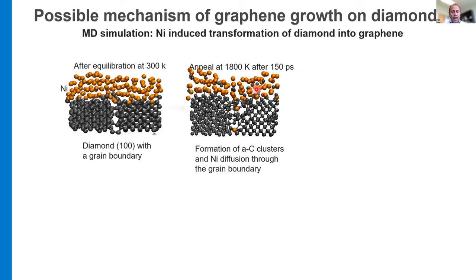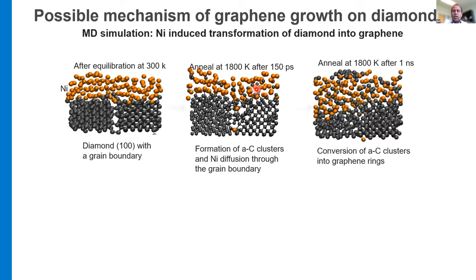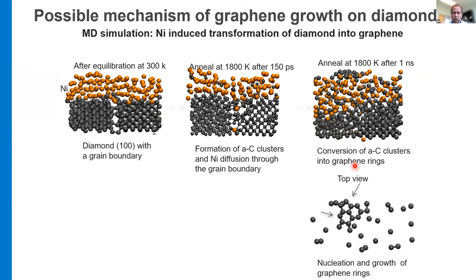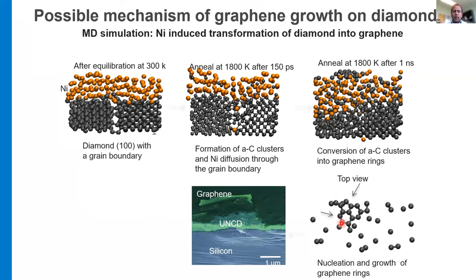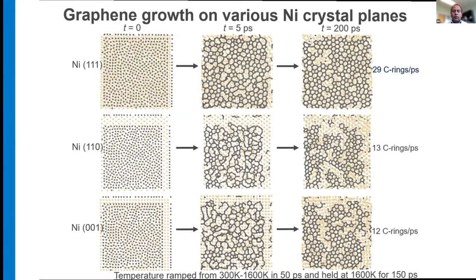So these grain boundaries act as a sink for nickel to diffuse very rapidly. But during this process, a catalytic reaction happens, and there is a conversion of the diamond underneath into amorphous carbon clusters. And then what we see here is the formation of a nickel island that nucleates this amorphous carbon into this ring-like structure, which is the initial nucleation phase of the graphene growth, and that's how the graphene grows.